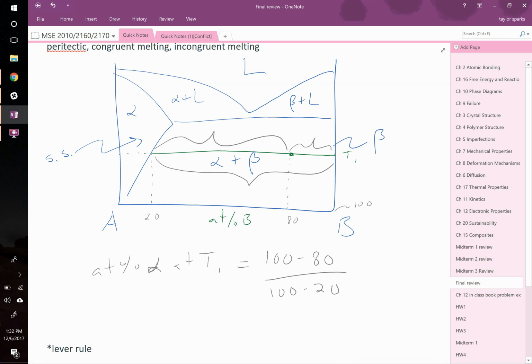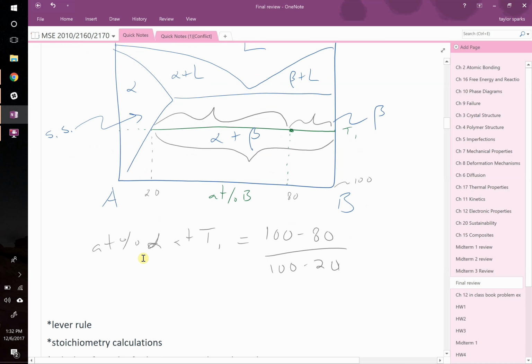Anything else I can answer on this? Arthur? For the amount of beta? Yeah, let's write it. So this is the lever rule. We could also do the lever rule to figure out the atomic percent of beta at temperature T1. It would be equal to 100 minus 80 over 100 minus 20. So if this one was 25%, am I doing that right? Yeah, 25%. This one would be 75%.